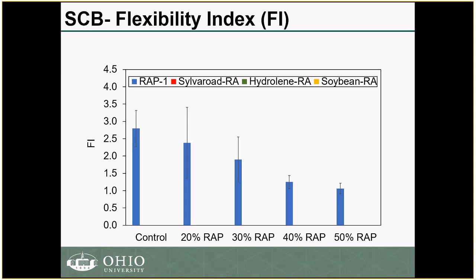Basically, what we can see here is that as you increase the RAP percentage, your flexibility index is lower, indicating that it is more prone to fatigue cracking. We can see as well that although we used a softer binder in the 30%, 40%, 50% RAP, this did not really help in improving the fatigue cracking resistance of those mixtures.